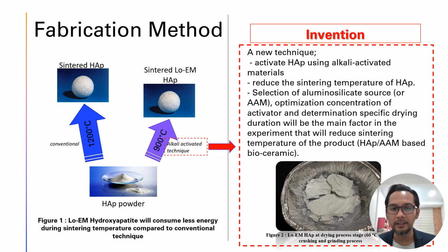A new technique activates HAP using alkaline activated material. The precursor, as I mentioned just now, is metakaolin, so it reduces the sintering temperature of hydroxyapatite. So we did the selection of aluminum silicate source, optimization of the concentration of activator, and determination of the specific drying duration. This is what we did prior to achieving this product. And even for this invention, we already have a patent filing.